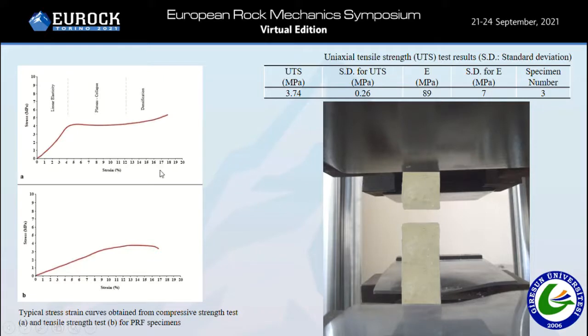This is a picture from the uniaxial direct tensile strength test of the polyurethane rigid foam material, which is a high density PRF material. In this figure's A part, you see now the stress strain behavior of this material under uniaxial compression, and the B section is for the uniaxial tensile strength test. It should be noted here that a high density polyurethane rigid foam is used within this study.